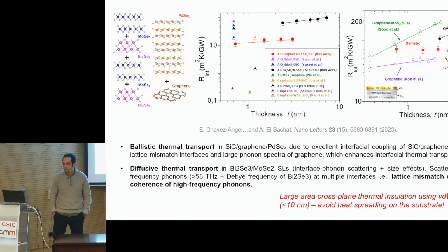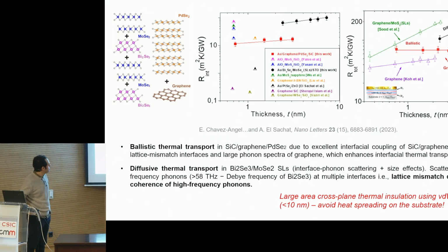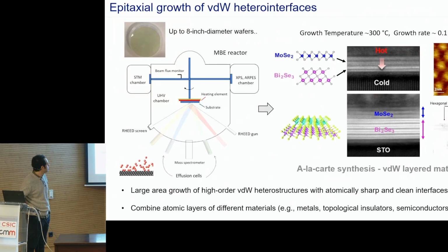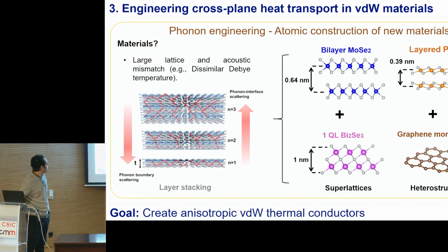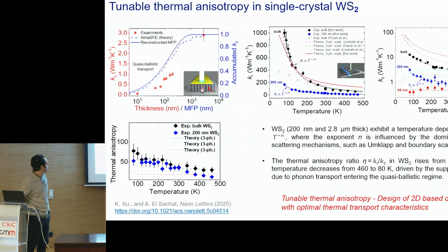And in the previous slide that you showed, the conductivity increases as a function of the thickness. In this case, you have only one material. In the previous slide, the cross-plane heat flux increases as a function of the thickness of your system. I guess this one, for example, the top left. Yes, exactly. Do you have an idea why you have a better conduction when you increase the thickness? Because I would expect more scattering because the van der Waals interaction is different for the different layers.